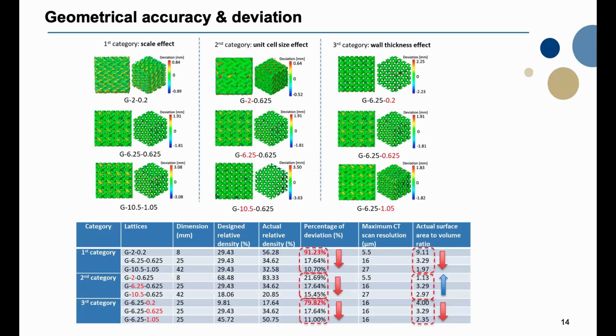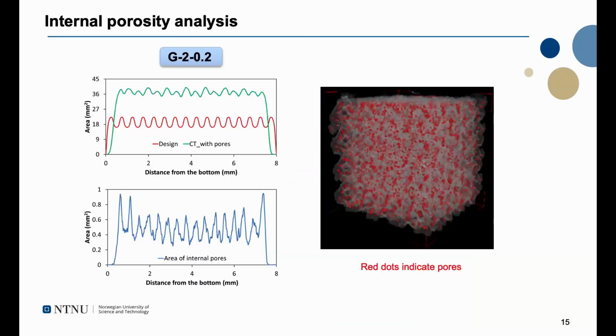And also, we calculate the actual surface area to volume ratio, and most of them have a similar trend to the percentage of the deviation. And we can see that for the lattices with the wall thickness effect, the lattices with the thinnest wall thickness also have the largest percentage of deviation in this category.